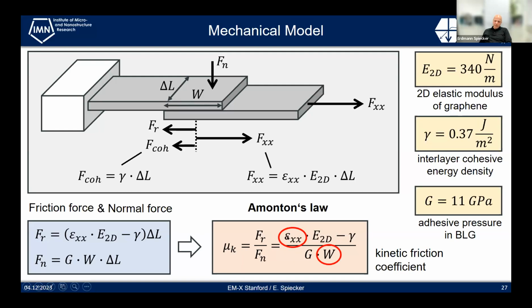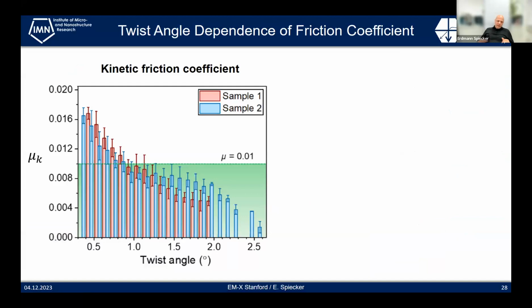And just to remind you, we measure two quantities. So one is the epsilon xx, it's a strain in the monolayer graphene, which we use as a spring constant. And so to speak, we have here a spring constant, and we measure the extension of that spring. And we measure, of course, the width of the overlapping region, which we directly get from the image. By doing that, Xin derived this kinetic friction coefficient, which also depends now on the twist angle.